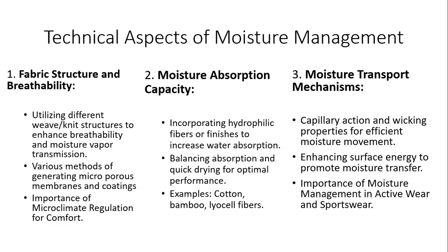Why is that? It is because although it has a good absorption capacity, it makes chemical bonding with the water molecule. Specifically, the hydrogen bonding is a very strong bonding. So therefore, when it comes to the evaporation, it does not get quickly evaporated. That is, we need to make a balance between the absorption and the quick evaporation. So sometimes, for the cotton fabric, they try to engineer the absorption capacities through the use of certain after finishes so that the absorption level is a little bit lower.